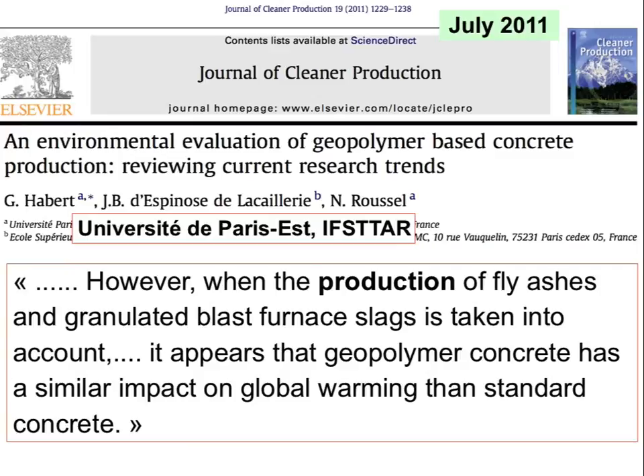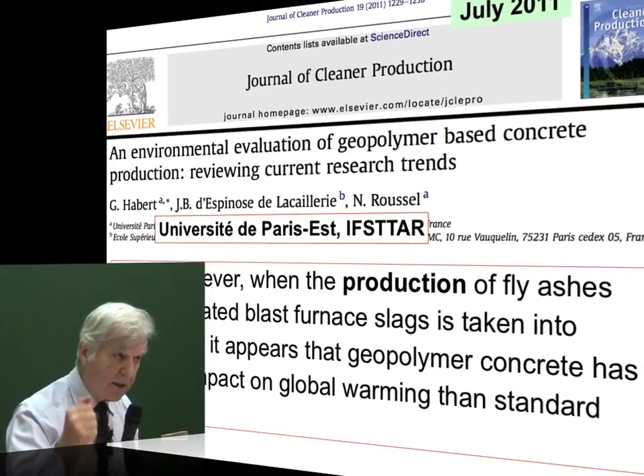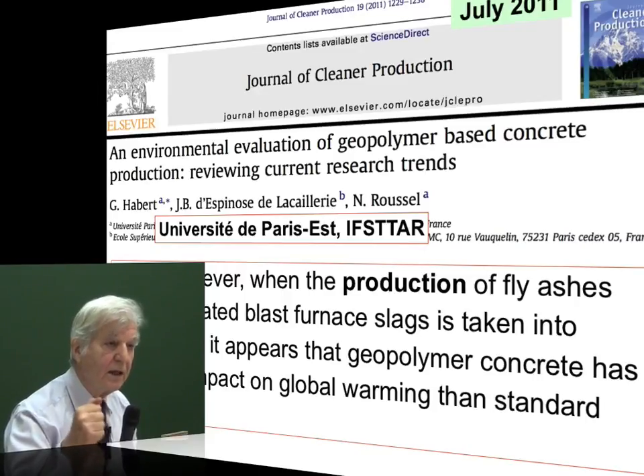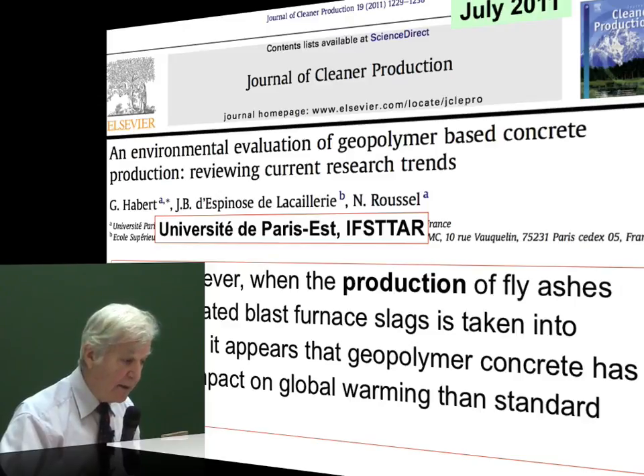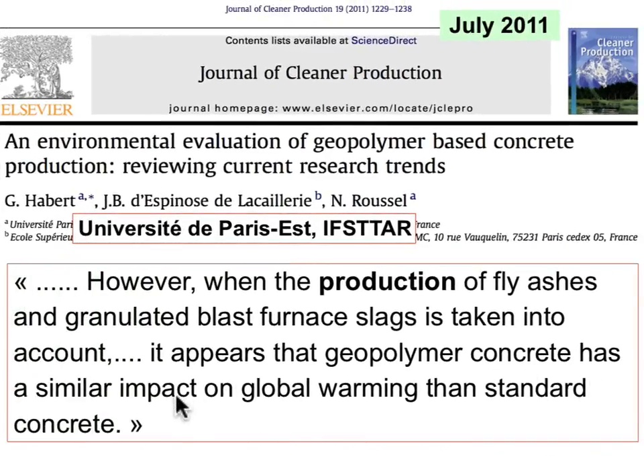and they wrote, well, what we have done was by taking the raw materials, fly ash and slag, as a waste, that is, not allocating any CO2 to it. But this is wrong in terms of calculation. From a scientific point of view, we must compare something totally different. Namely, we must take into account the CO2 emission if we would have manufactured the fly ash, manufactured the slag to make the geopolymer cement. And in that case, it appears that geopolymer concrete has a similar impact on global warming than standard concrete.